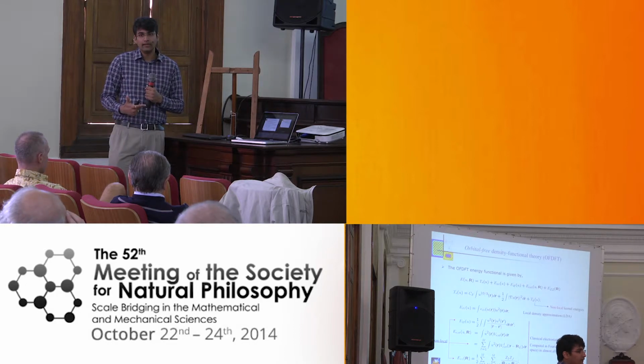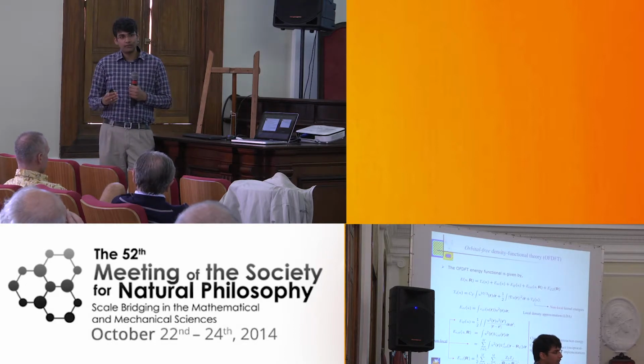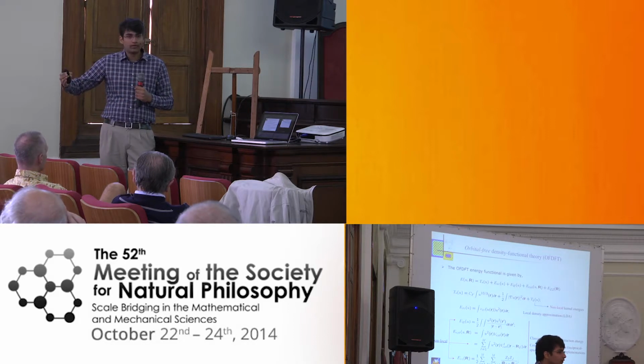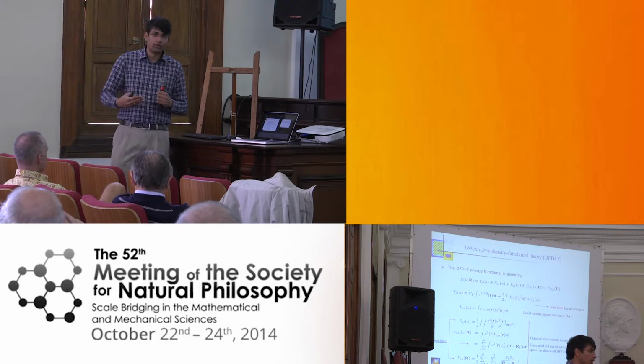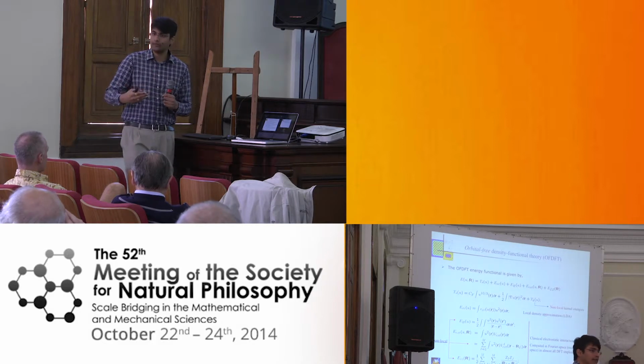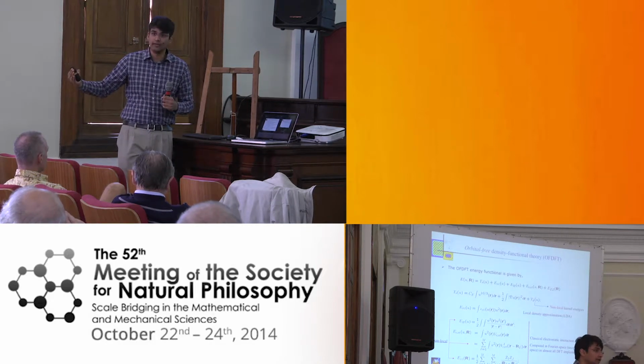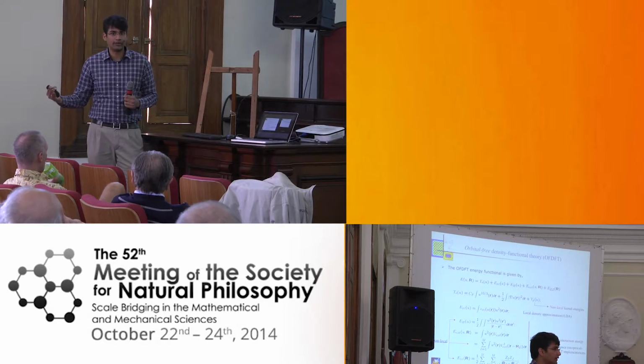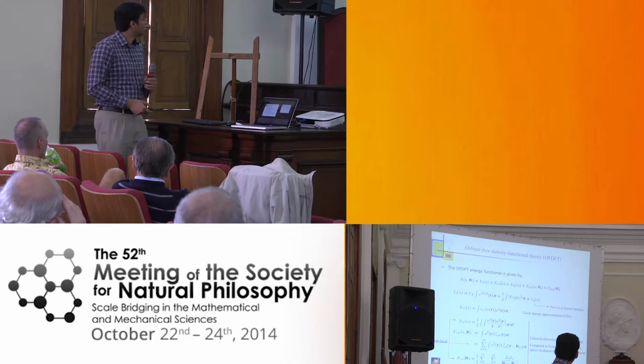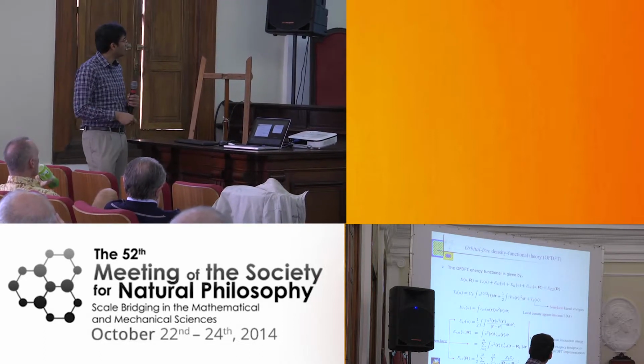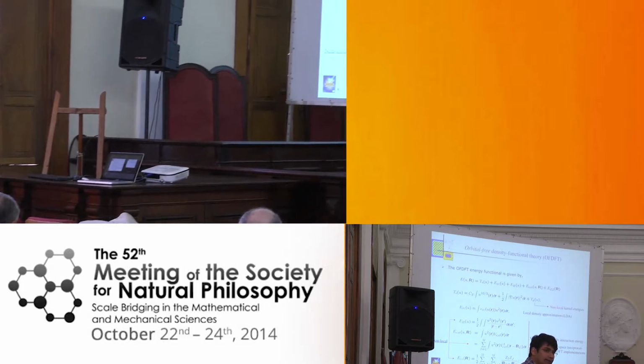And then the second thing is that Fourier space calculations involve a plane wave basis. And the plane wave basis gives the same spatial resolution everywhere in the domain. And that's not good when we are looking at defects in materials. We probably want to use more spatial resolution where necessary, and then we could potentially coarse grain far away. So it's not an adaptive basis set. So that's the second disadvantage. So that's why we sought to reformulate this whole thing in real space.